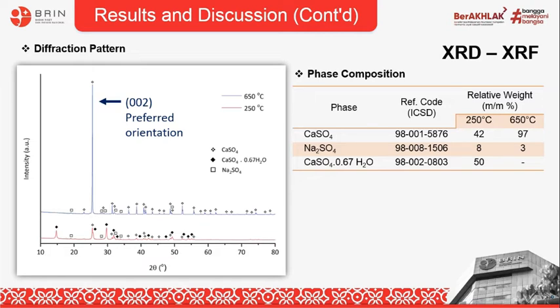The anhydrate phase after heating at 650 Celsius degree was found with very high concentration, more than 95%, though thenardite sodium sulfate was found as a mineral phase in both samples. The excess precursors of sodium sulfate remained in the powder due to incomplete washing process before calcination at 650 Celsius degree, and probably formed double salts with calcium sulfate as a solid solution.